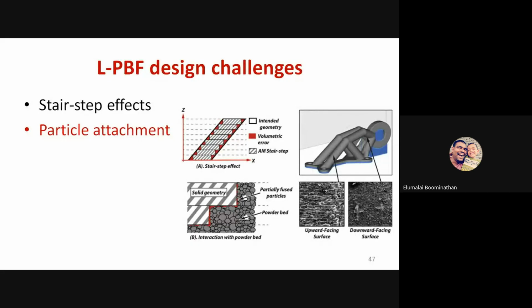And another issue apart from the stair step effect is particle attachment in the SLS or SLM process. The melt pool attracts the surrounding unmolten or solid particles. These solid particles usually attach to the part being built. And also the upward facing surface has different properties than the downward facing surface because of the particle attachment. So while designing and while orienting for printing, you have to consider these two factors: one is the stair step effect and the other is the particle attachment effect.